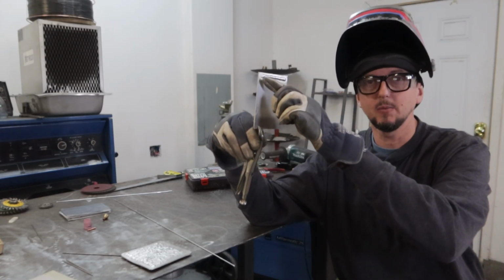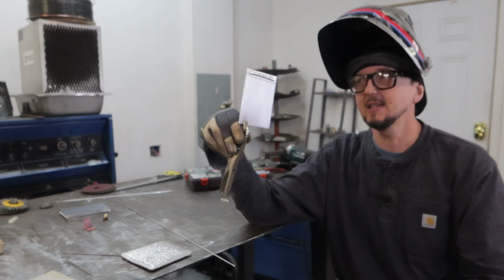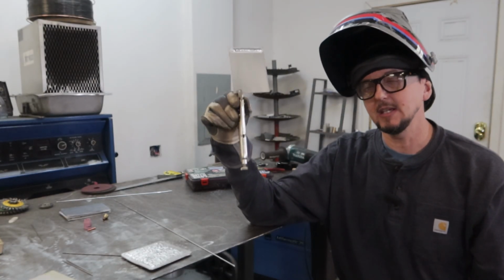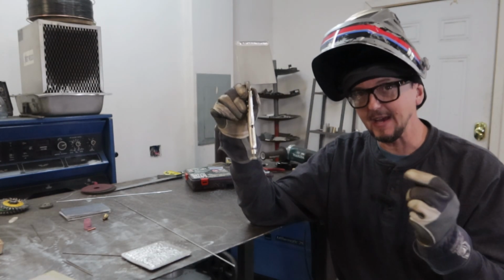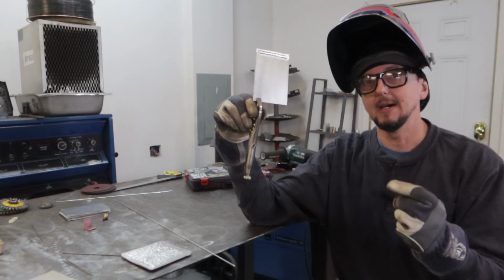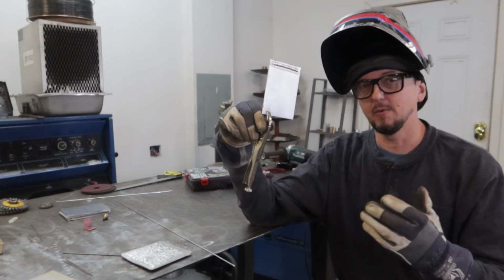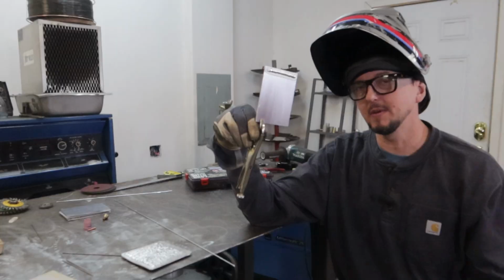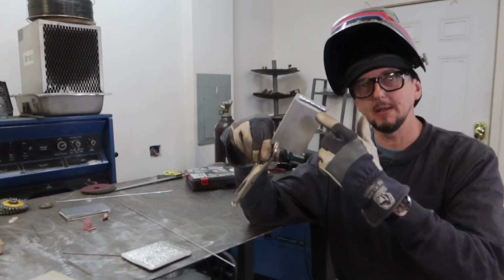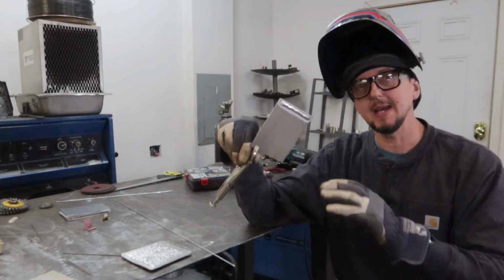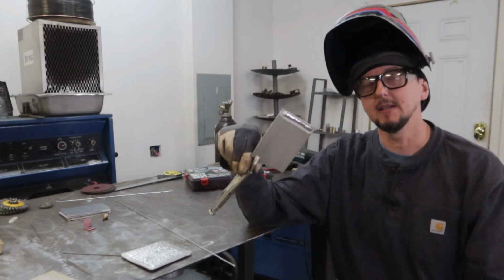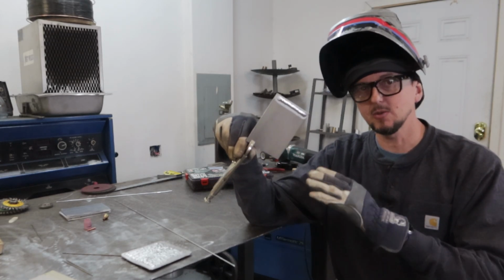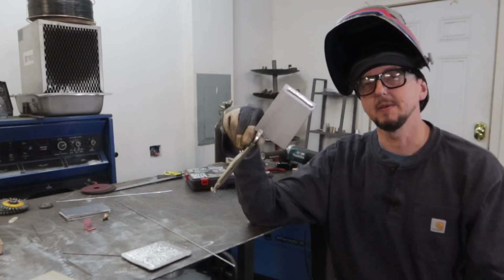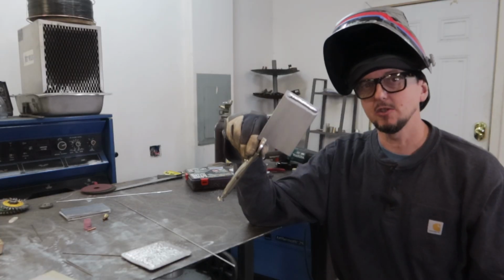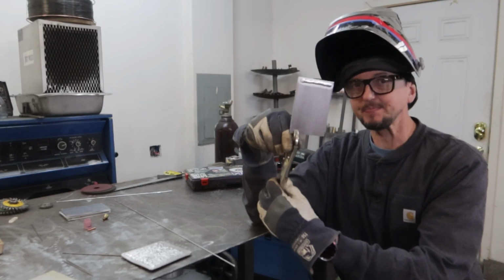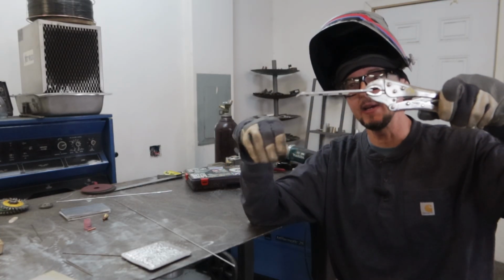So now we're going to start to surface this. And like I said before, especially, I've got a fairly fast travel speed. So I can get away with maybe 3 or 4 beads in a row, maybe a little bit more than that. But you're probably only going to be able to do maybe 2 or 3 at a time, then let your plate cool down a little bit, or maybe switch between a few different plates so that you can manage your heat effectively. And then also we're going to get high rates of distortion.